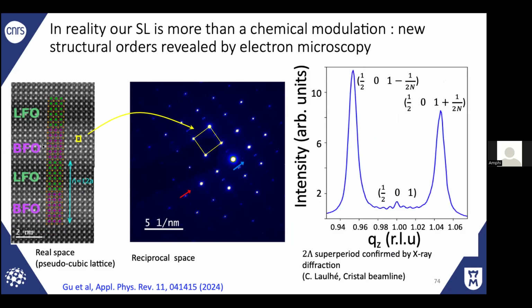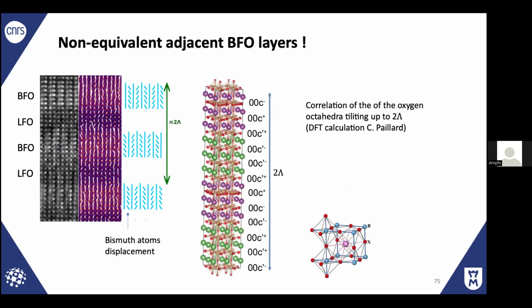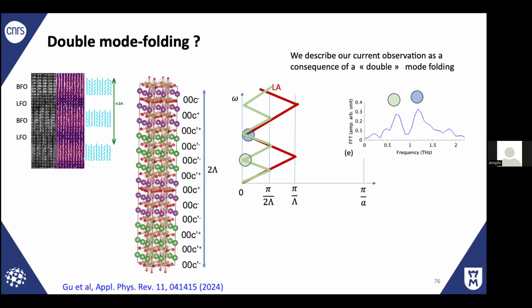This has also been observed with Claire by X-ray diffraction. That superstructure here has been observed as well by X-ray diffraction. And finally, it comes from the fact that if you take into account that the system is a ferroelectric, the ferroelectric order, if you look at that, is not the same from two neighbor BFO layers. And in that case, it induces the doubling of the superlattices. So we have, let's say, a double mode folding. That's the way we explained that situation. Okay.